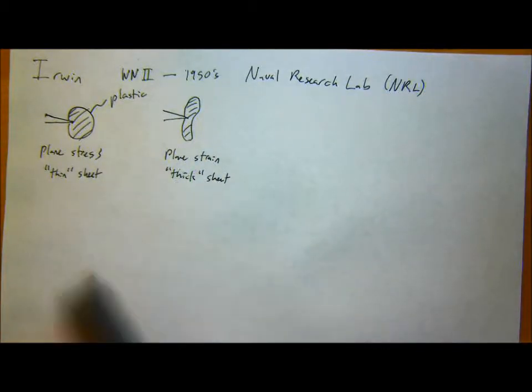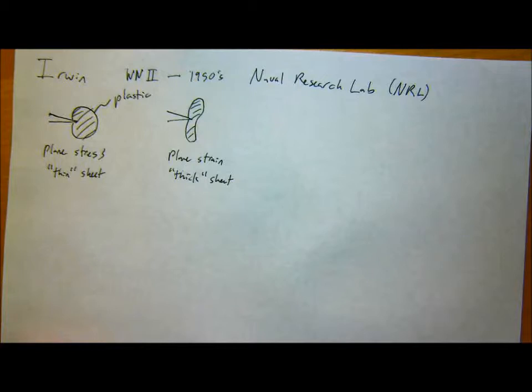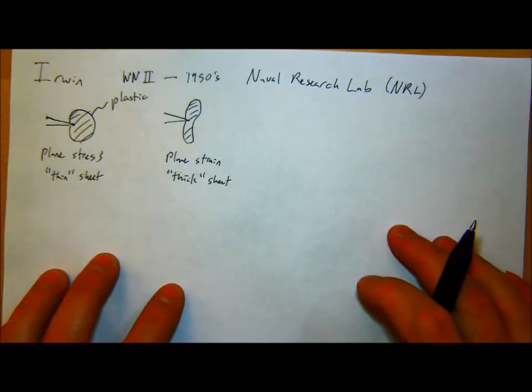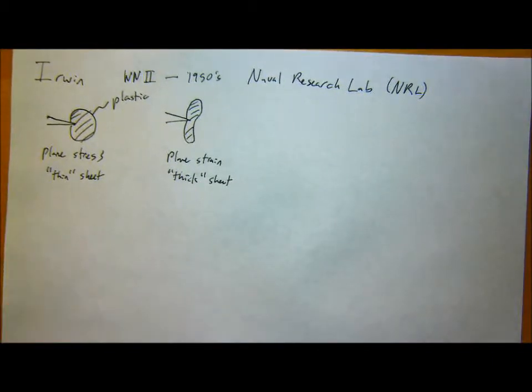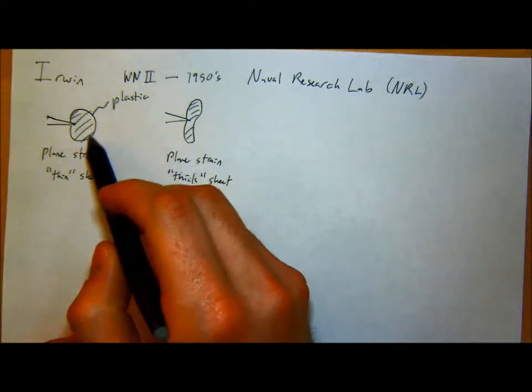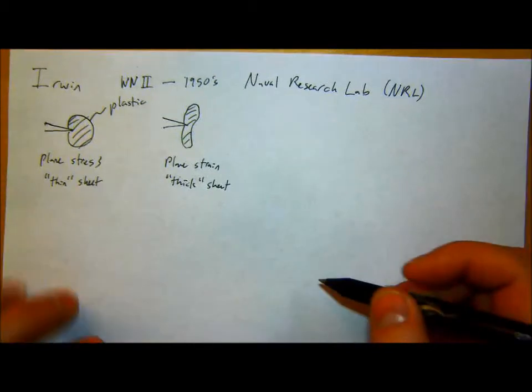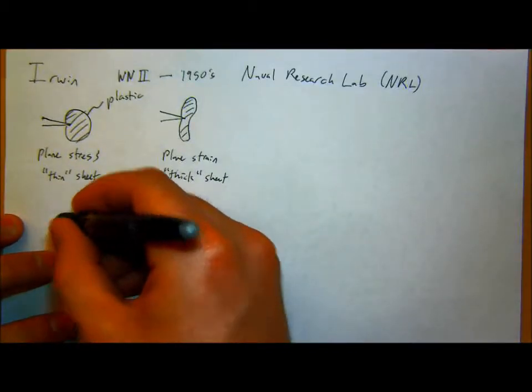Basically he then thought about, all right, realistically around this tip of the crack, you have some plastic deformation region. So when I look at a crack, what I'm idealizing this crack as is some very sharp shape. It's never actually that. There's always some blunting of the crack because of the plastic region.